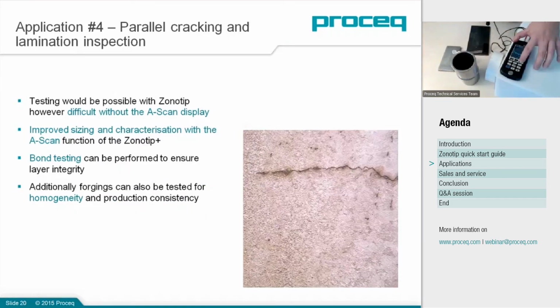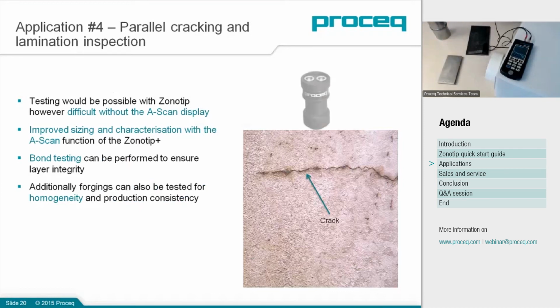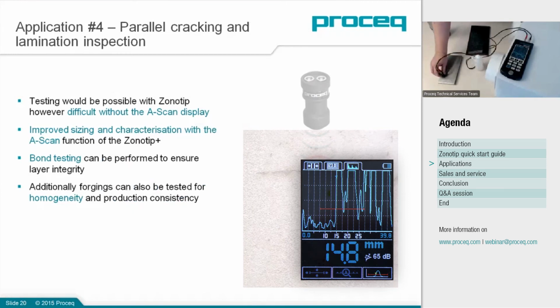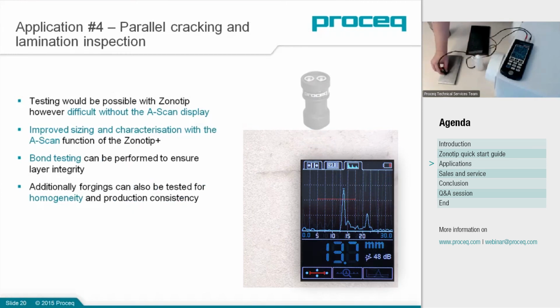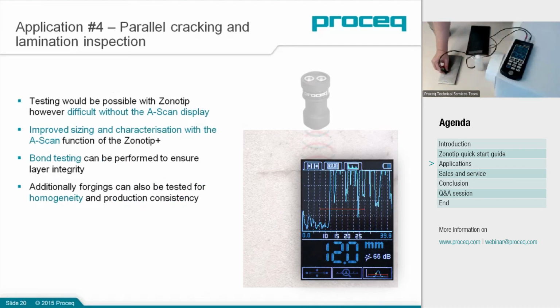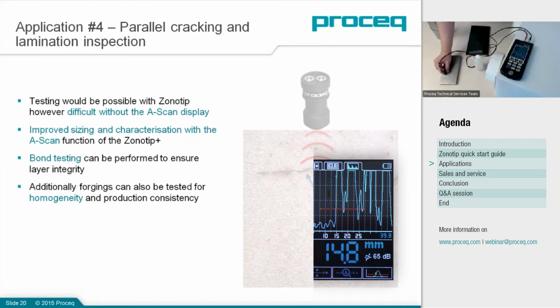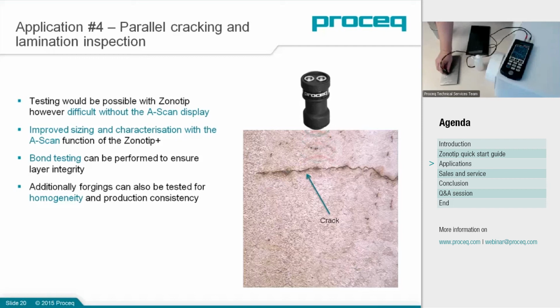Okay, next application we've got for you is detecting possible cracks and flaws. Move this out of the way. I've got a plate here which has a pre-manufactured delamination in it, for example. So what you get is your normal reading of the thickness of the plate, and you can scan along, and as you get to a delamination, you can see there, we're scanning over the delamination now, it's giving a reading of 12. The normal thickness of the plate is 14.8, but as we move over the delamination, we get a reading of 12. So that means we've got a defect.